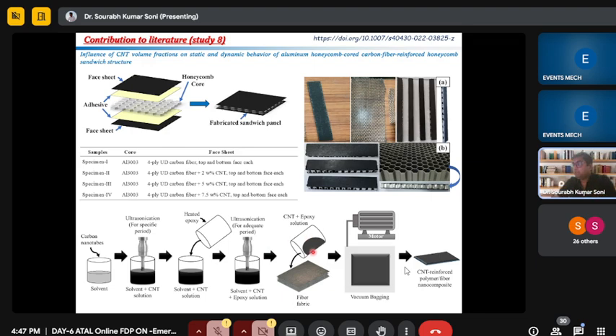Then this CNT plus epoxy solution we have poured on the carbon fiber, and then we perform the vacuum bagging to produce the CNT reinforced polymer fiber nanocomposite. Polymer is the epoxy, fiber is the carbon, and reinforcement is the CNT. So we can say more than one reinforcement.